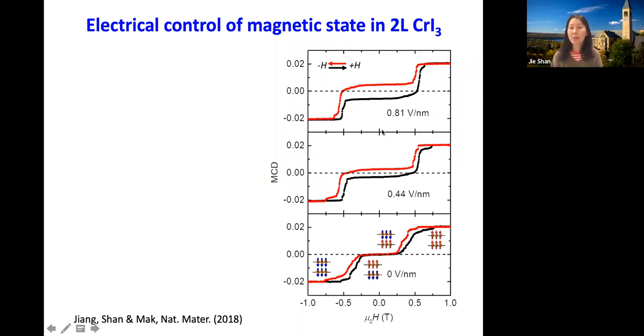Now let's look at the bilayer. In the absence of electrical fields, we have seen earlier that there is zero magnetization at zero field. And when you increase the magnetic field, you switch the spin. It's a spin flip transition, and it's a first order transition. So we have magnetic hysteresis, and that's expected. And now if we increase the field perpendicular to the layer, suddenly the magnetization is no longer zero. And if you keep increasing the field, the magnetization increases.